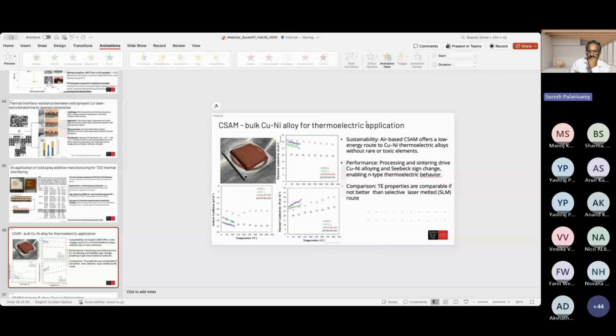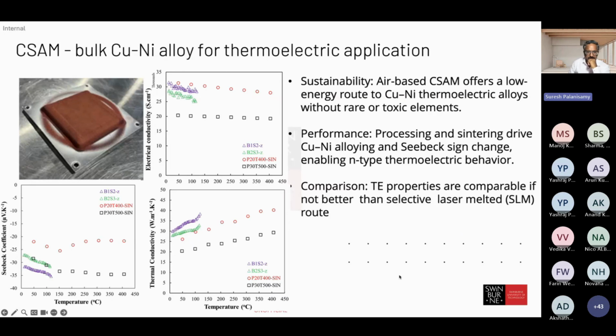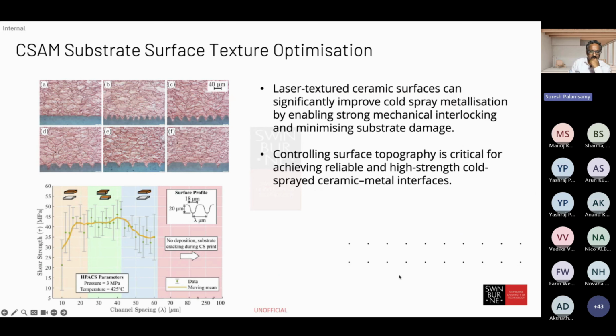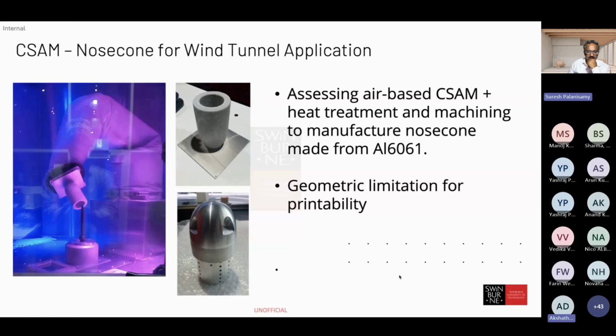Maybe a quick question on the powder particle size. We use around 50 to under 80 microns in some cases, or 20 to 50 microns also. So a few different ranges of powder particle size are used, depending on the machine type and the process type. But most commonly, the 20 to 80 micron range, or the 60 micron range, is a common range.